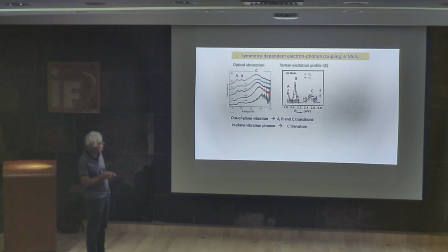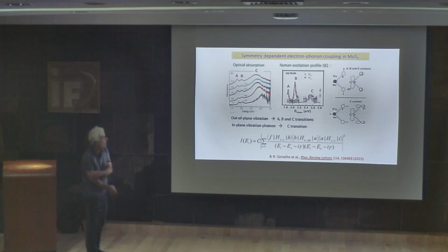We can see that when you have resonance with the A exciton and the B exciton, we have the enhancement of the out-of-plane mode. But the in-plane mode was not enhanced by the A and the B exciton, but both of them were enhanced by the C exciton. Then what we realized here is that the reason only the out-of-plane mode is enhanced by the A and B exciton is because the electron-phonon coupling is symmetry dependent.